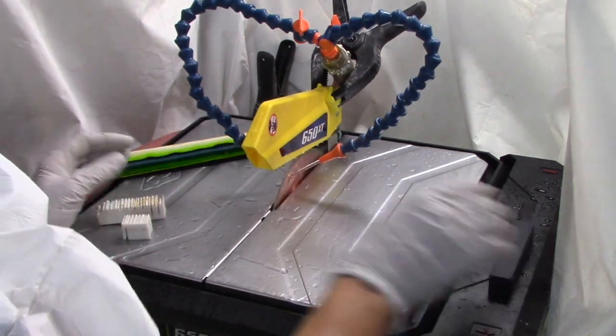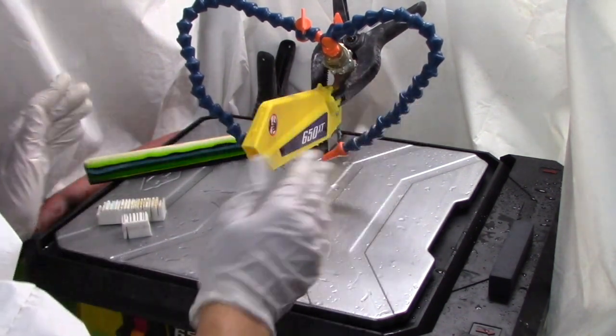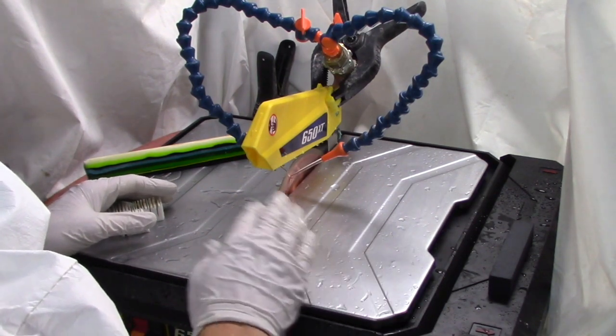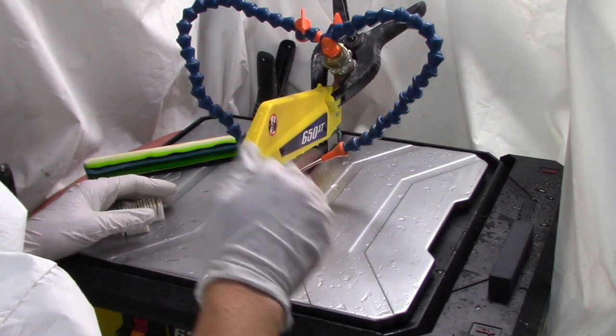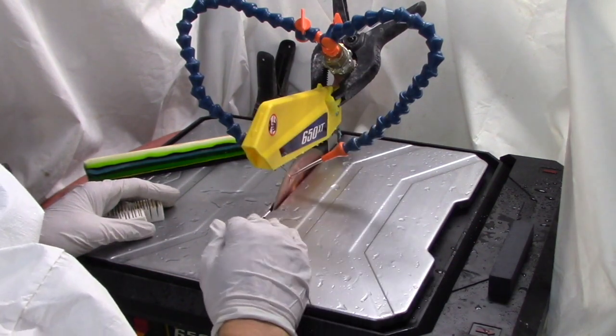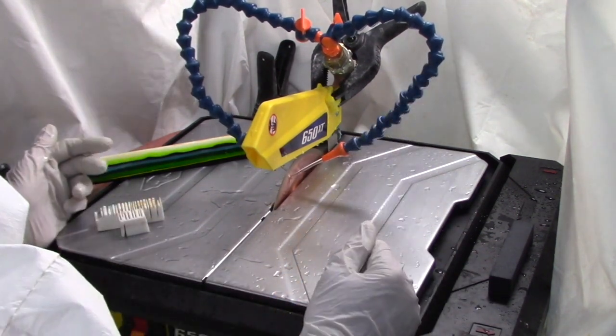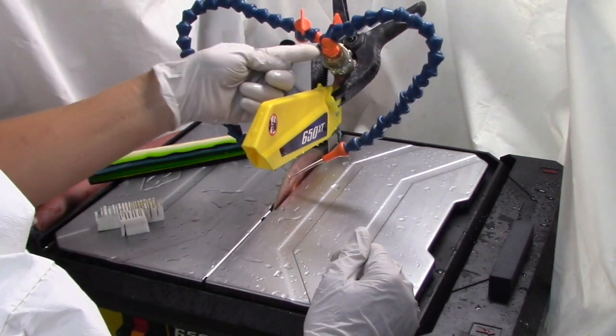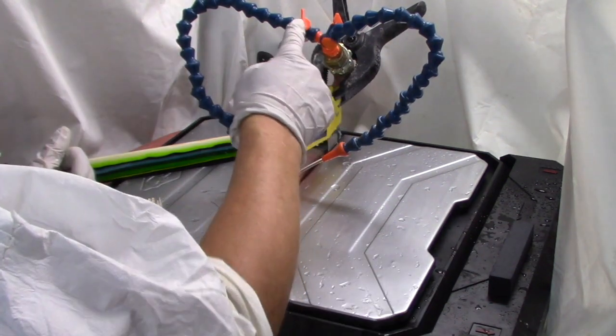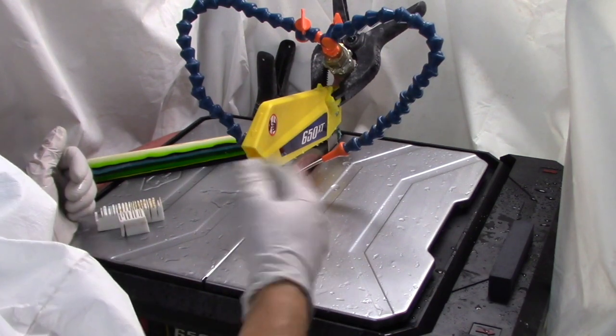The most important thing out of all of this is water — lots and lots of fresh cold water. There's a reservoir below the saw, but it's not enough water, and the water heats up after it's recirculated so many times, which causes chipping and a dull blade. I bought this little lock-line kit, hooked it up to my garden hose — you can see it's clamped on, coming from the outside. You just turn it on, position these little nozzles towards the blade, and you're ready to cut.